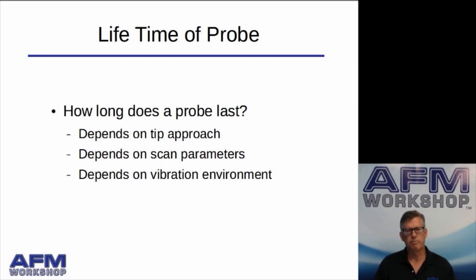So if you can master these 3 things, that is getting a good tip approach, having the right scan parameters, and being in the right vibration environment, a probe can last a week, even a month. You'll see some people that are very experienced with running AFMs will use a probe for a while and they'll take it out of the microscope and put it back in a box. Then when they want to use that probe again, they'll take it back out and use it. So again, this really depends on several factors.